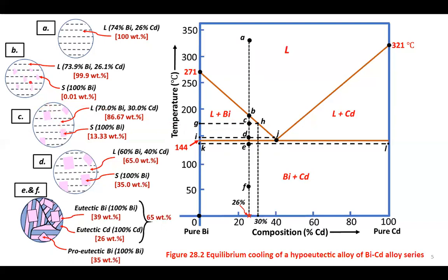Generally the critical nuclei are shown to grow into the form of dendrites, right? Because in most metallic systems, the solid phase that is growing is something which is highly metallic. But see students, this is an exceptional case. This is a type 2 system. This is a system where the two elements are drastically different from each other in chemical nature. And generally a type 2 system will get formed when one of the constituent elements is very metallic, the other is very less metallic. The same is the case here.